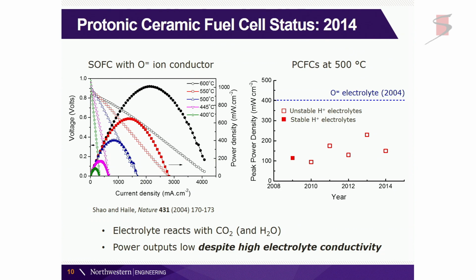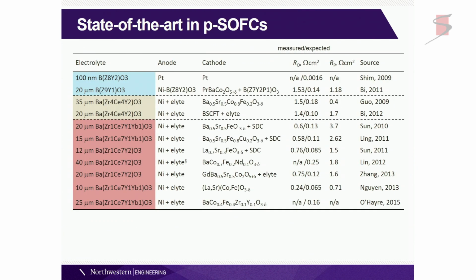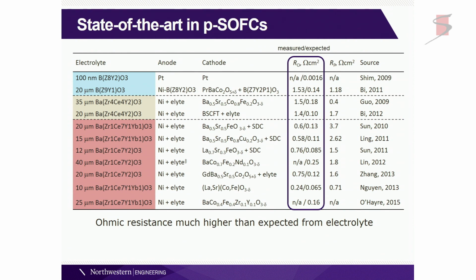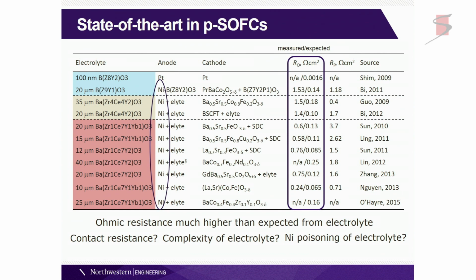So we wanted to understand why they weren't doing as well as they should, and could we come up with a better electrolyte. This is a bit of an eye chart, but what I want to point out to you is that for all of those systems that had low power densities, the ohmic contribution, which should be due to the electrolyte, was much higher than what you expected. The measured value was many times an order of magnitude higher than what you expect from the electrolyte. So either the electrolyte itself was not good in some way, or there was some contact resistance, or these very complex chemistries were having difficulty in terms of fabrication, or perhaps there was poisoning from the nickel in the anode component poisoning the electrolyte. So we said, we need to really understand this and both create better electrolytes and establish the issues of the contact resistance.